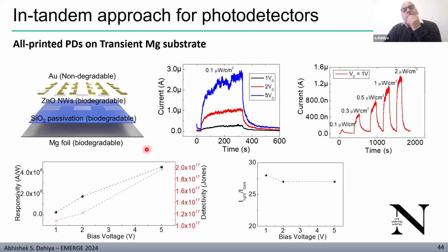The process was moved to biodegradable substrates. Here we have fabricated again on the magnesium substrate. So we take the magnesium foil, we first passivate using silicon oxide, we transfer zinc oxide nanowire using the in tandem approach, and then we bring our printer to print gold electrodes on it.